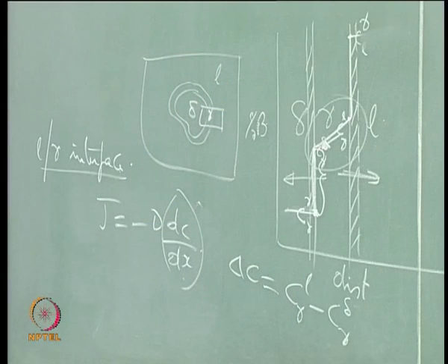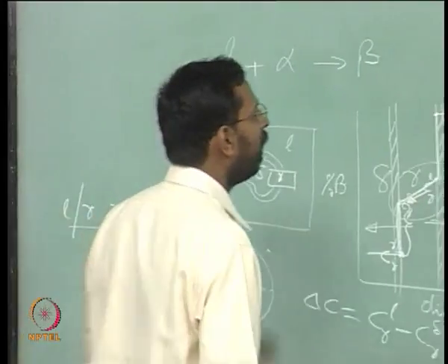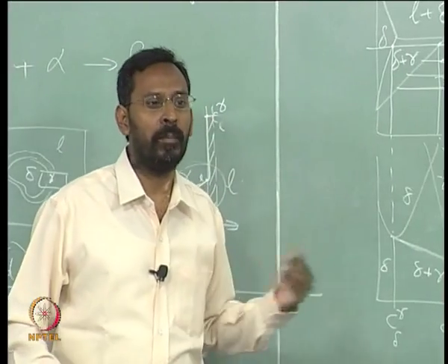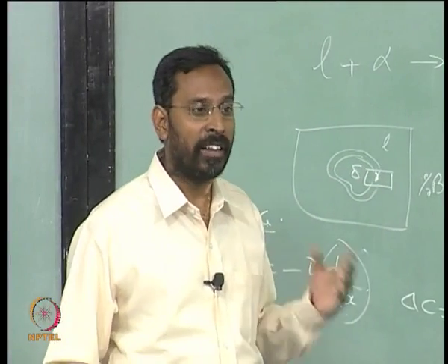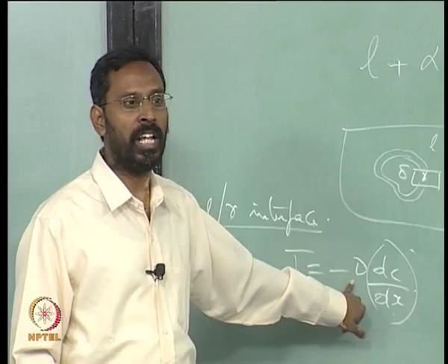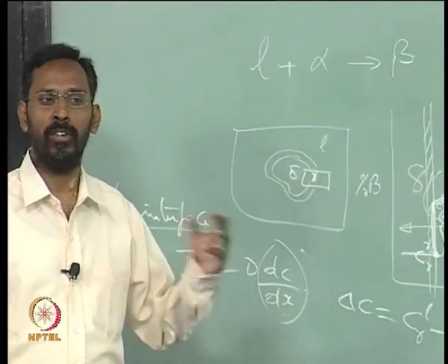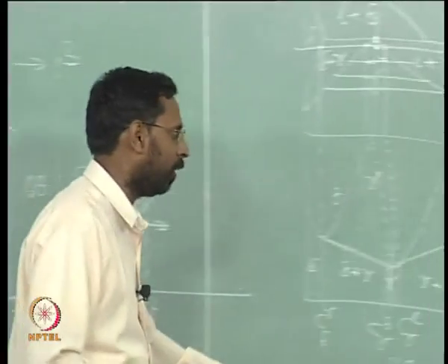So, you see that initially it starts at a faster rate, but as a function of time you will slowly see it decreases. That is the reason why, at very high undercoolings, there may not be any peritectic reaction significantly occurring, because at that temperature D itself is slow. D is slow and this is larger. So, both of them will lead you to this, and this is something which we need to understand.